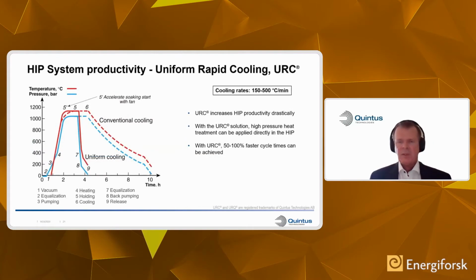Quintus presses come in a number of variations. One, I would say more standard type, is our Uniform Rapid Cooling. Depending on the size of the HIP, we can reach between 150 and 500 C per minute cooling rate. And this is 100% controllable, so you can basically set the cooling rate that you want. It will definitely shorten your cycle times in the HIP and increase your productivity.